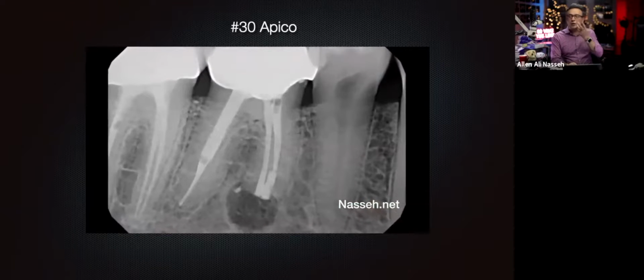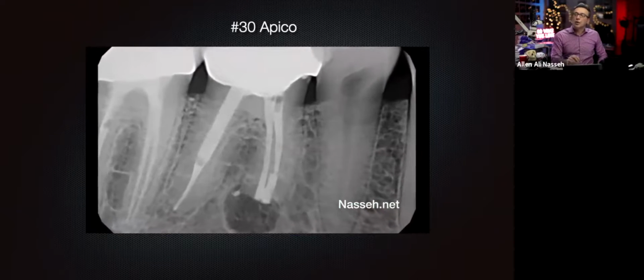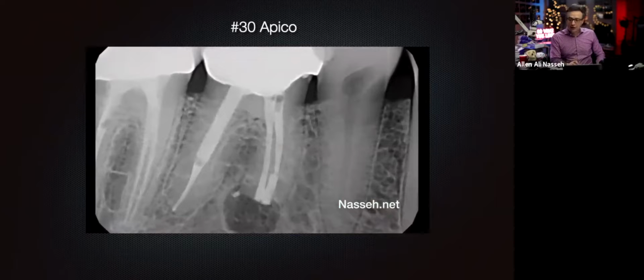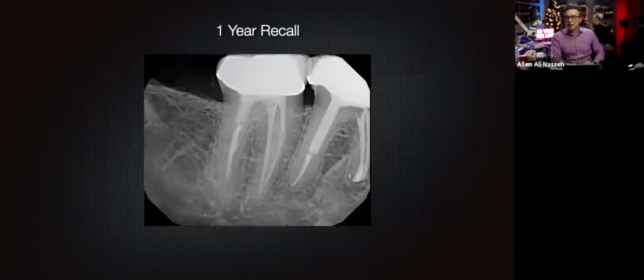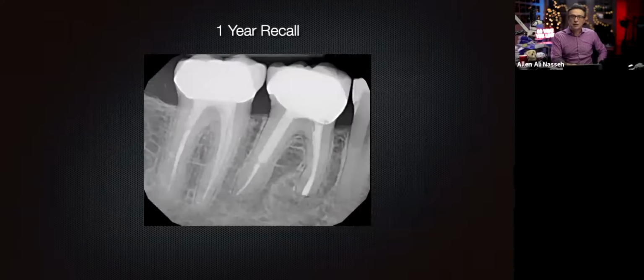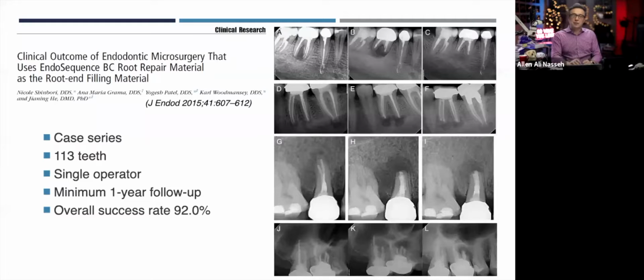Especially with the high flow, you have also a much more radio opaque retrofilling. So that's the best material to combine. I use the BC high flow and the BC putty fast set for this technique. And you can see your recall here. The lesion is filled up here with the bone. And I didn't even use a grafting material.